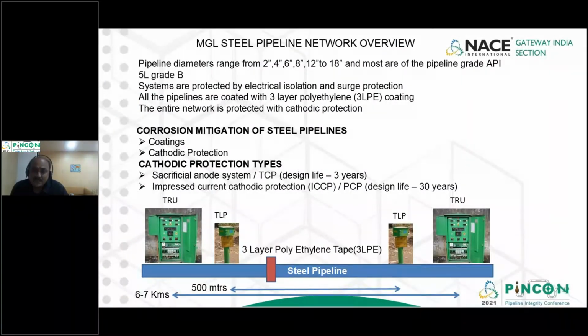Our steel pipeline diameters are 2 inch, 4 inch, 6 inch, 8 inch, 12 and 18. So almost all sizes of pipeline we have. The reason for having these is because we have district regulating stations which take in the gas from the tap off from the main line. So that would be around 4 inches. Some CNG stations have pipelines of 2 inches, and the branch lines are normally 6, 8, and 12 inches from the main line. And the pipeline is API 5L grade B.